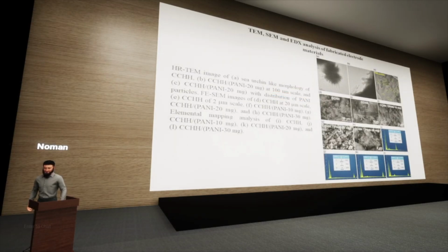If we talk about the SEM, TEM, and EDX analysis, we can very clearly see that this picture shows the sea urchin shape morphology, in which the needles are coming out of the spherical core. This is the more zoomed TEM image in which we can see the edges of the needles, and this picture shows the distribution of the particles inside the material. SEM analysis also showed a similar kind of morphology, and EDX analysis showed that carbon, oxygen, and cobalt, the key elements of our precursor materials, are found in all the samples. And with 30 milligram addition of polyaniline, the maximum amount of carbon was found.